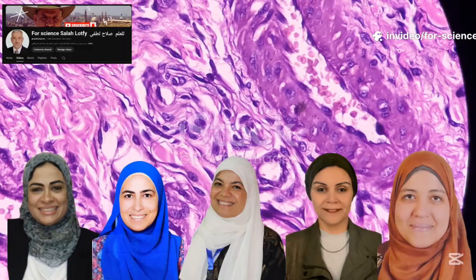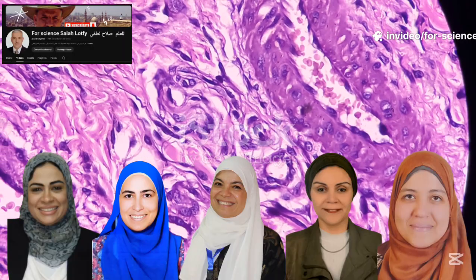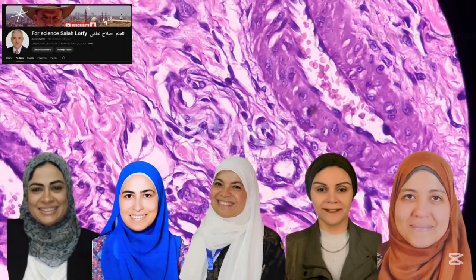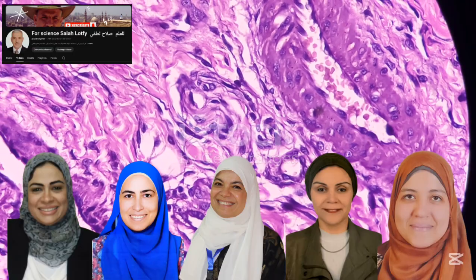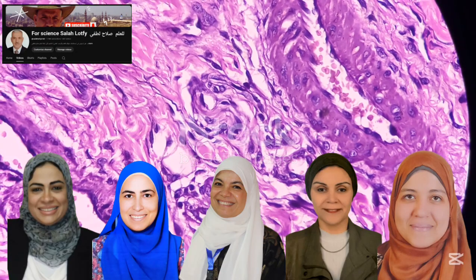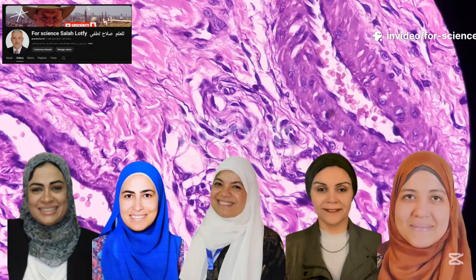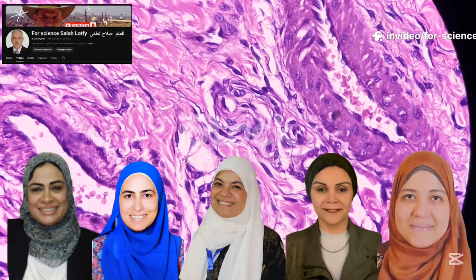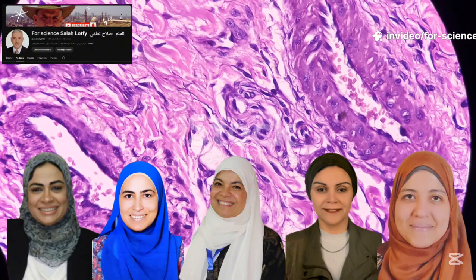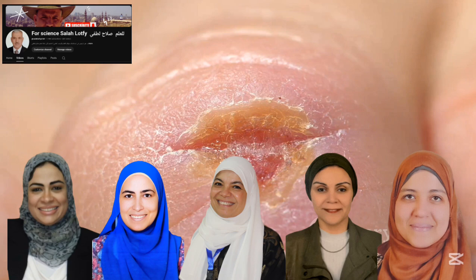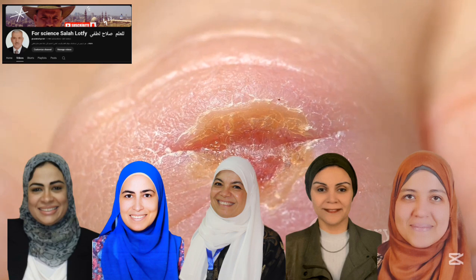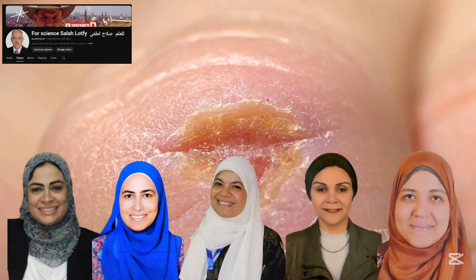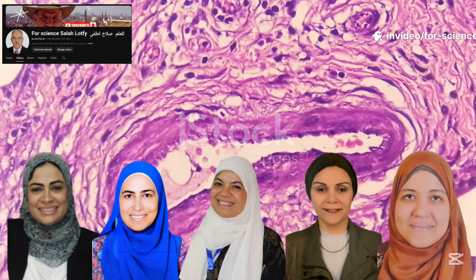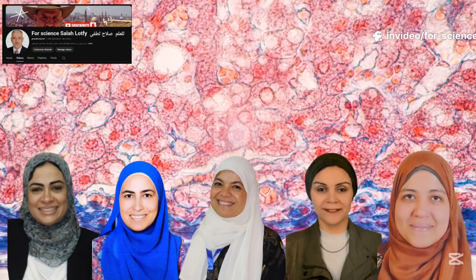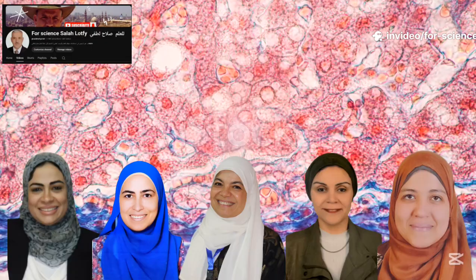Second, minimal inflammation. The lavender oil actively modulated the inflammatory response, promoting a rapid transition to the proliferative healing phase. Histology showed a significant reduction in neutrophils and a shift towards M2 macrophages, the pro-resolution phenotype essential for tissue repair, creating a microenvironment conducive to healing. Third, strong, healthy granulation tissue formation. This new tissue filling the wound space was dense and highly vascularized. We observed robust angiogenesis, the formation of new blood vessels, critical for supplying oxygen and nutrients.